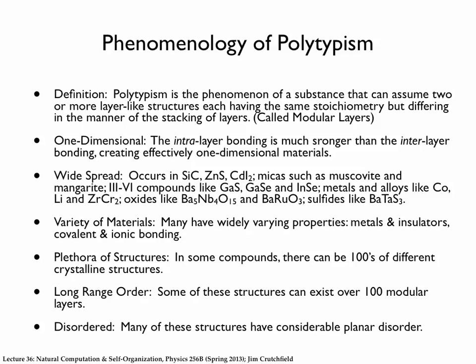The phenomenon that you find is that many of these compounds, silicon carbide being one and zinc sulfide another, which I'll talk about in more detail later, can have not only considerable disordered stackings, which is primarily what we're interested in because this is a place that crystallography has historically had a problem addressing, but also many long-range periodic stackings. So we see these really funky crystals that may take 50 or 100 stacked layers to repeat over and over again. That phenomenon is probably described not by the interaction between adjacent or even far-removed layers, but by another type of structure called a giant screw dislocation.